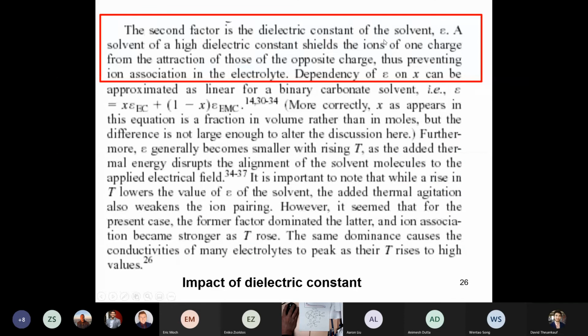The second factor is the dielectric constant of the solvent. A solvent of high dielectric constant shields the ions of one charge from the attraction of those of the opposite charge, thus preventing this ion pairing of the electrolyte. Okay, so higher dielectric constant can help prevent this ion pairing that is not a good thing.